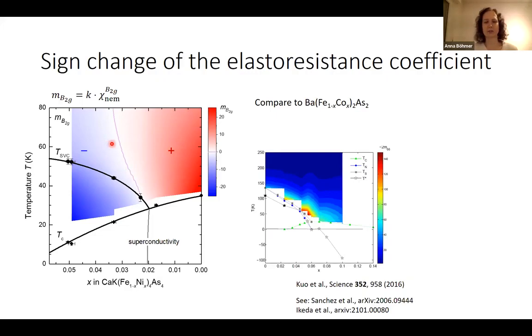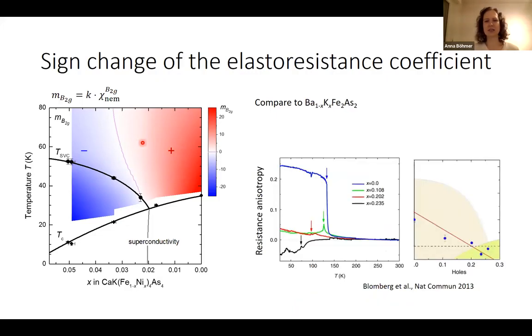there's a real sign change of the proportionality constant. And that's reminiscent of a result in the hole-doped 122 system. Here there's no elastoresistance data published to date, but there is a resistance anisotropy in strained or stressed samples. And the sign change was found there as well. So that seems to be related. And that comes from microscopic measurements of, well, scattering and Fermi surface changes, which was also explained here.